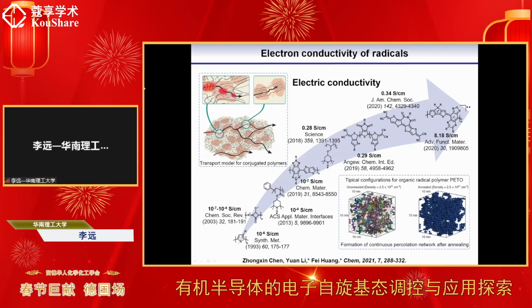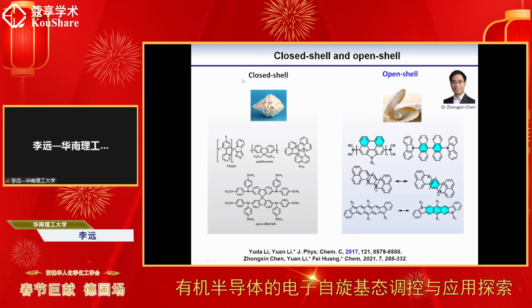And the closed shell and the open shell polyaromatic hydrocarbons, you can see, and the typical organic semiconductors usually are viewed as closed shell. For example, the polyfluorene and the typical electron-withdrawing, electron transport materials, and also the spiro-OMeTAD, this kind of closed shell. And this kind of materials are viewed as open shell radicals. And as I mentioned in previous slides, this kind of materials are very, very old. The mechanism is from the Chichibabin-type biradicals about more than 100 years ago. And the stability of this kind of compounds is very poor, and it cannot be stabilized in air for a long time.